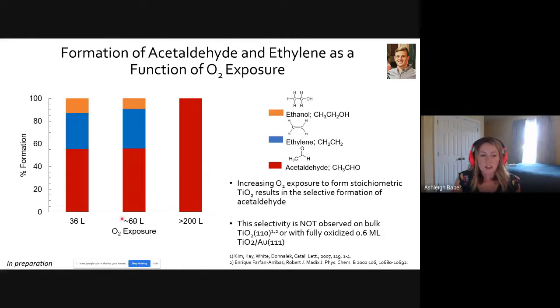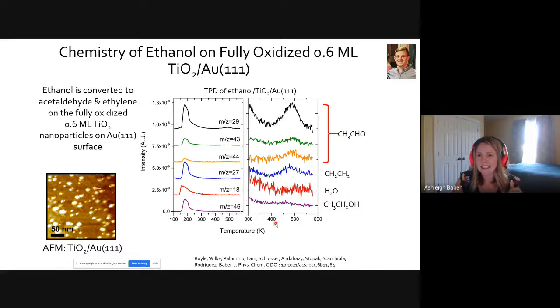So it looks like with an increase in oxygen exposure, we're able to drive that selective oxidation of ethanol into acetaldehyde. And you're probably thinking, okay, yeah, you add more oxygen and you see more oxidation. That makes sense. But that selectivity is not observed when you're looking at bulk titania 110. And we certainly didn't see that when we had larger nanoparticles of titania on the surface with a larger coverage. So there's this combination of making sure you have a lot of oxygen around, but also having small nanoparticles on the surface that is where we're able to see this kind of selectivity. So just as a reminder, we did not see that with the over half of a monolayer of titania on that surface.